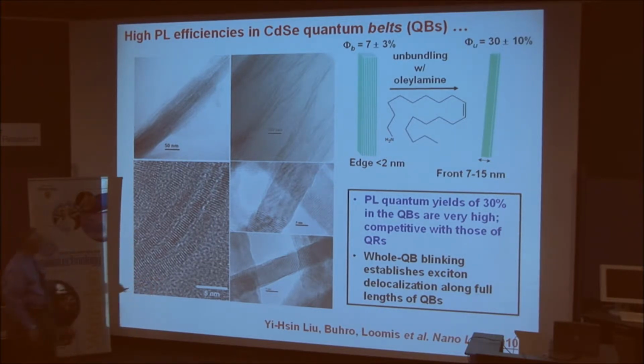And we never intended to work with quantum belts. We wanted small diameter wires, and there was a synthesis in the literature describing how to get small diameter wires. It turns out that our SLS method, the catalyzed method, has a limitation. We can really only make 4 or 5 nanometer wires at the smallest. It's very hard for us using that method to get smaller, but a lot of interesting things happen with smaller diameter wires, so I desperately wanted to have some.